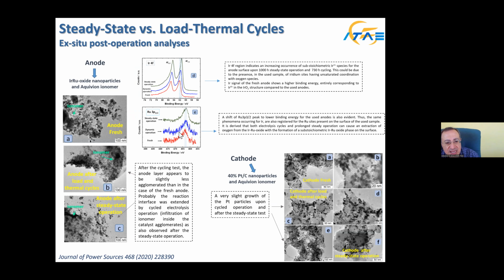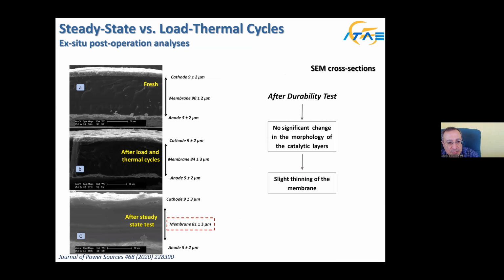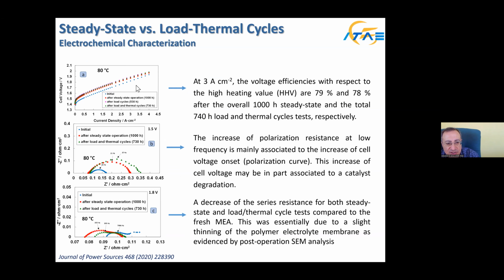We can see here by XPS analysis that we have a change in the oxidation state, but also loss of ruthenium with time. This is the drawback that has caused a loss in this diagram, an increase of the cell voltage.